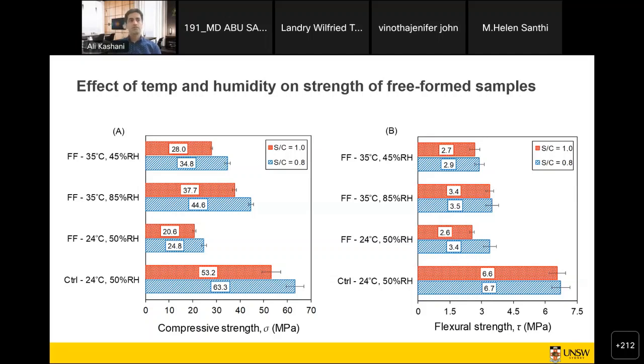And as you can see, if you take out the samples and put them in different conditions, we get much lower strength. If the humidity is good, so if the area is humid, that can compensate a bit. But if you put the samples in a low temperature and 50% relative humidity, as you can see, the strength development is less than half of the same material that is properly cured.